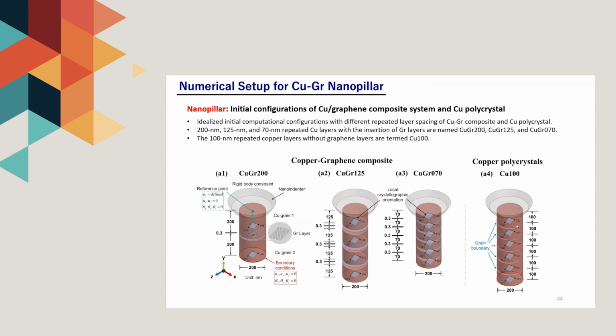The thickness of the graphene layer is approximately 0.3 nanometers, so it is modeled as a membrane element. Each copper layer has its local crystallographic orientation. The rigid body constraint and displacement-controlled loading are applied to the nano indenter. The loading strain rate is 0.002 per second.